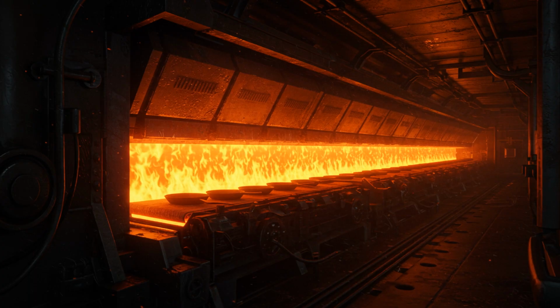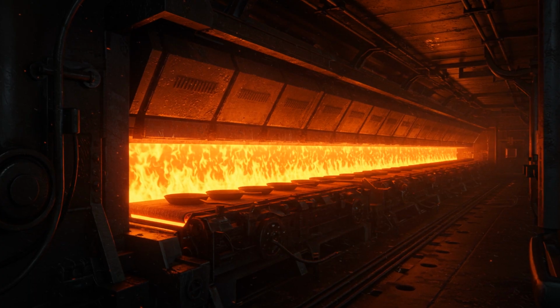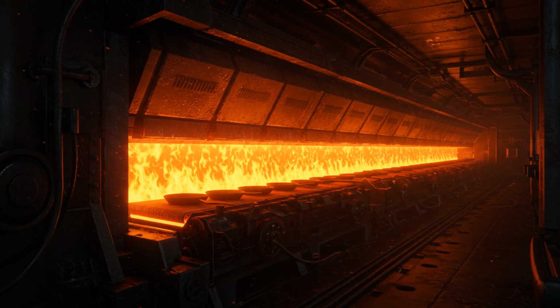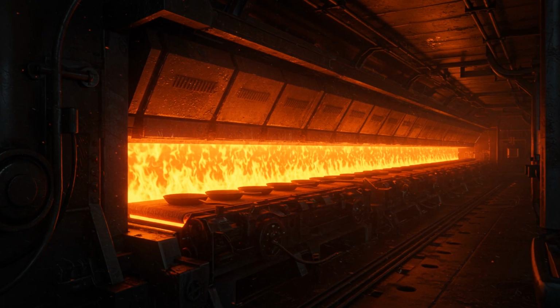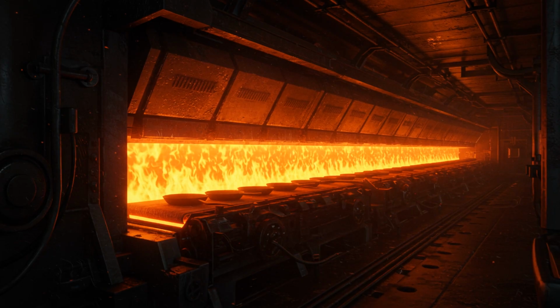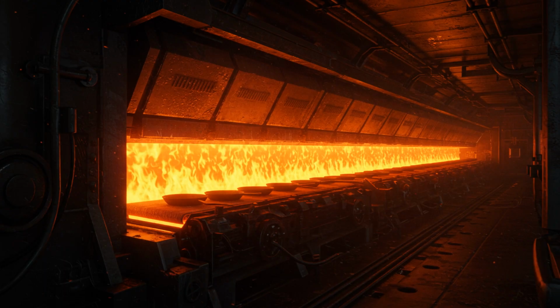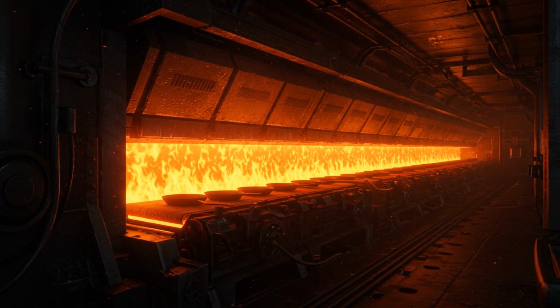If the temperature is too low, the film won't fuse and it will flake off. If it's too high, the PTFE will actually begin to decompose into toxic gases. Precision sensors monitor the oven's atmosphere every second. As the heat peaks, the primer and topcoat layers undergo an interdiffusion process. The polymer chains from different layers tangle together at the boundary, creating a single, unified coating that is now physically part of the pan structure.